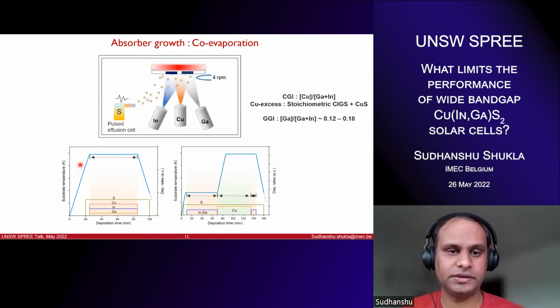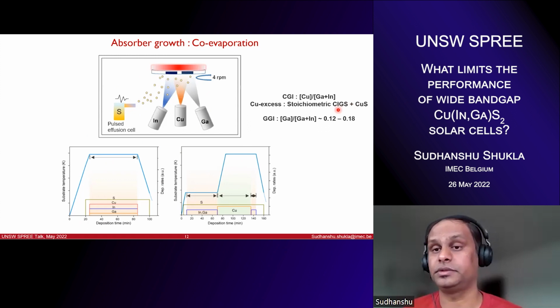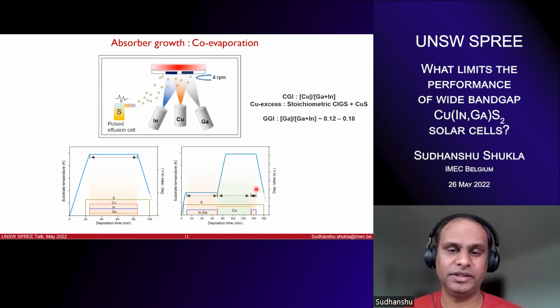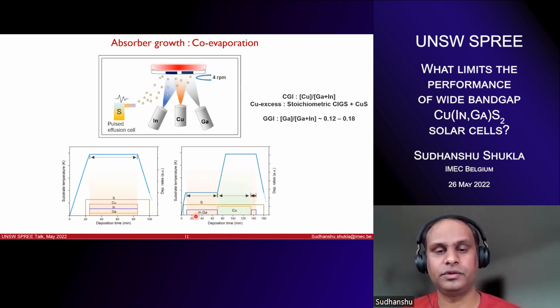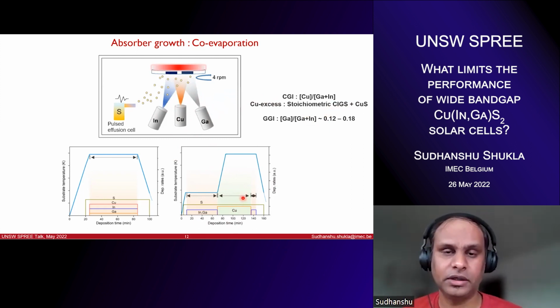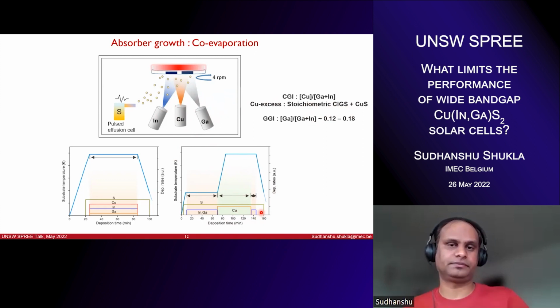We adopted this single stage growth procedure where we just evaporate all the elements at once. This is a single stage deposition process. And we also did a 2-stage process to make copper rich CIGS. And we did 3-stage. So we first evaporated indium gallium in the first stage. The second stage was copper evaporation, so when it becomes copper rich, we monitor it by checking the emissivity of the film. When it transitions from stoichiometric CIGS to copper rich CIS, then we did the third stage evaporation.